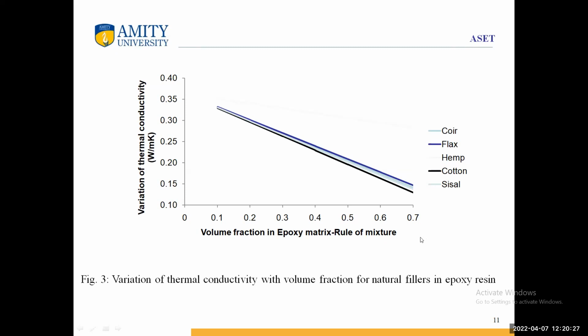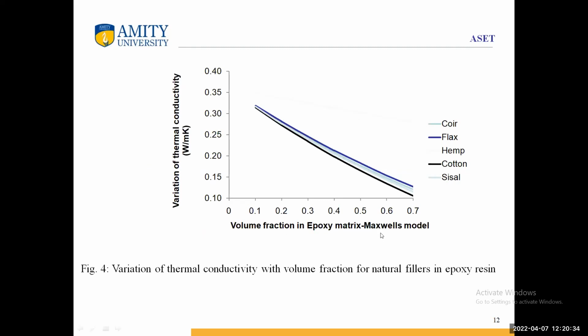Similarly, it can be tested by other models also. In the next graph, sir, it is tested by the Maxwell model, where they give the equations for the same. Here also the same pattern is observed, but the property values are too high. Up to 10% it is the highest value, and at 70% it is close to 0.1. So the Maxwell model shows a downward trend, with values very close to 0.1 watt per meter Kelvin as we go to higher volume percentages. So different models are tested for the same fibers, fillers, and same epoxy materials.